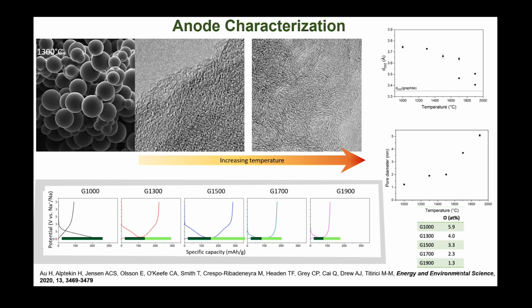So, making a very long story short, we looked at electrochemistry, we looked at ideal interlayer spacing, we looked at the pore size, we looked at the defects and oxygen content, we went a lot to synchrotron, and we've realized that in order to have the best possible hard carbon, you need to have an interlayer spacing between these disordered graphene layers of between 3.6 and 3.7 angstroms.